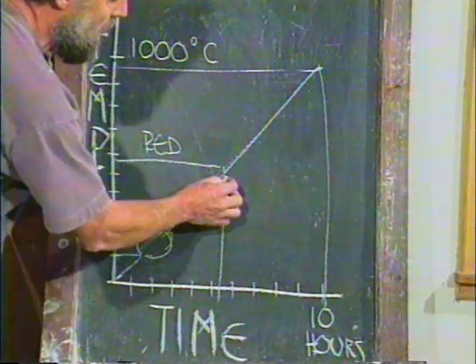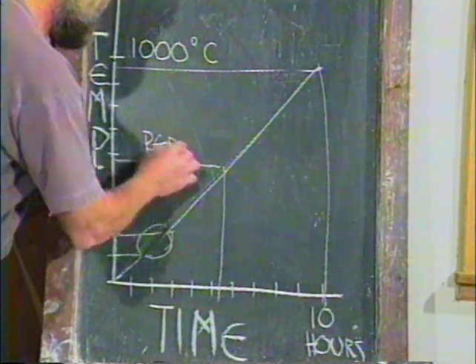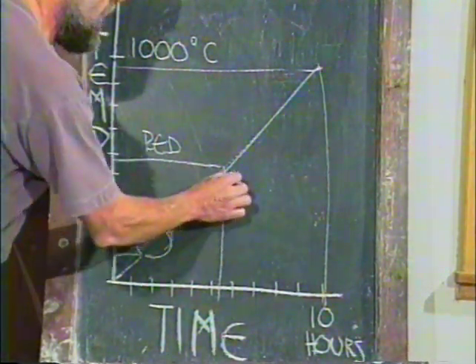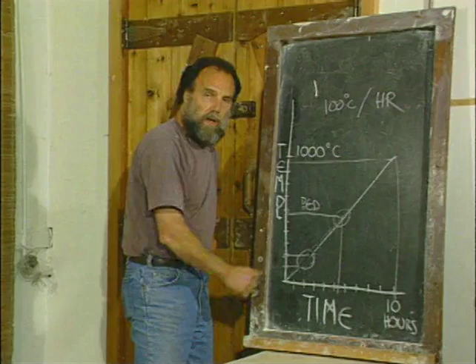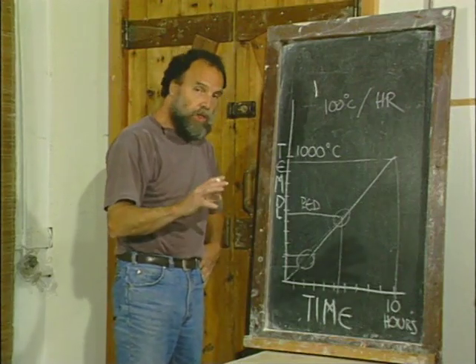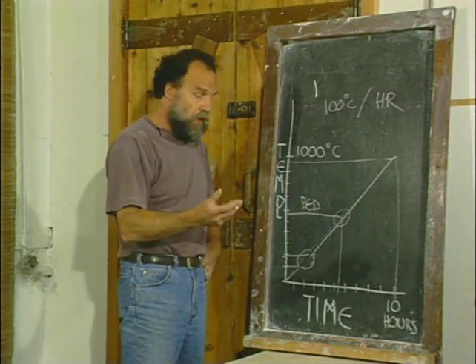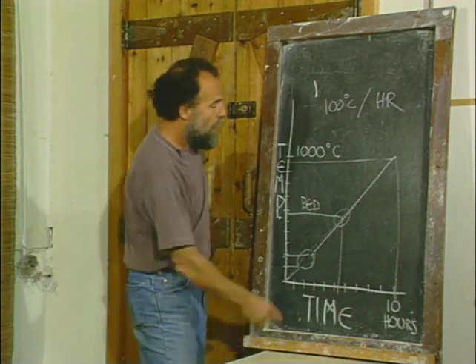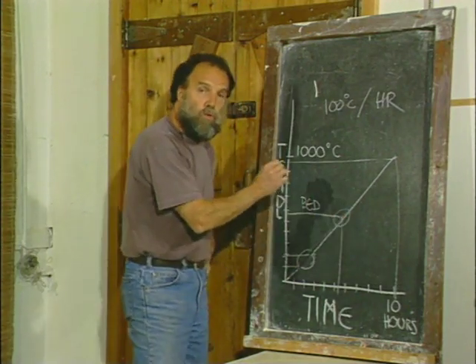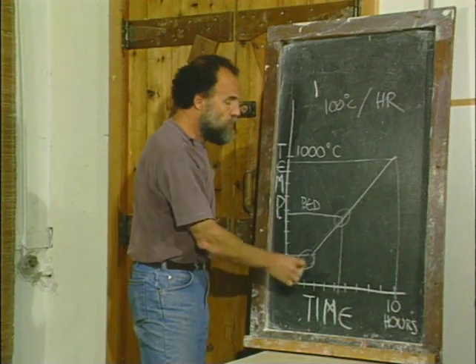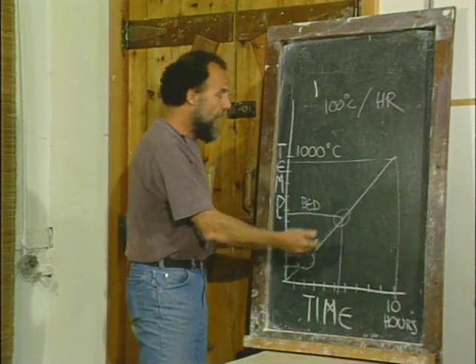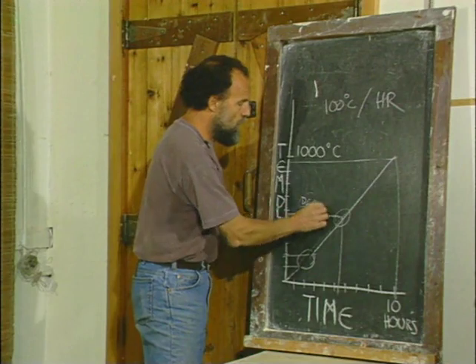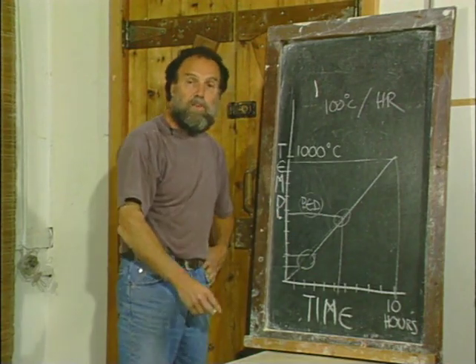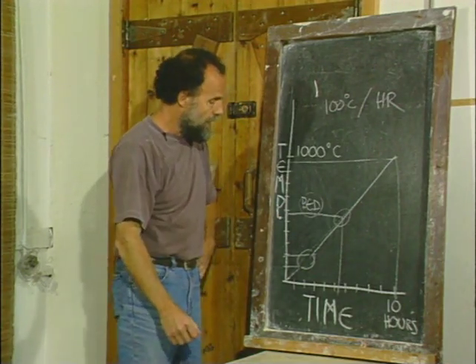The second point that's of particular interest is around this lowest visible red stage, up around here, where the actual crystal structure of the clay is changing a little bit, and there's a dimension change associated with that, and it's important that you don't fire too quickly through this point. So what you don't want to be is on the high setting as you go through the red at around 550 to 570 degrees Celsius.